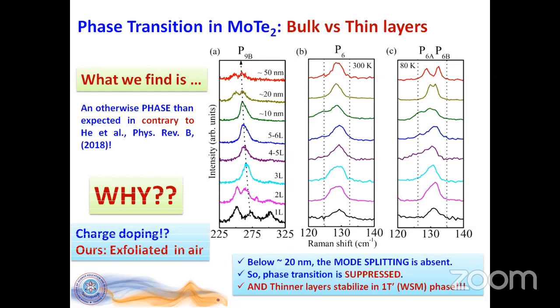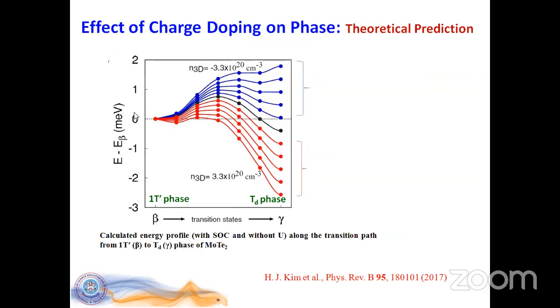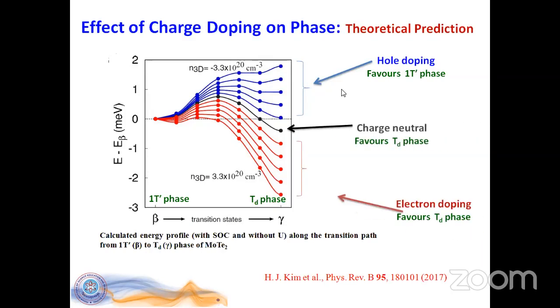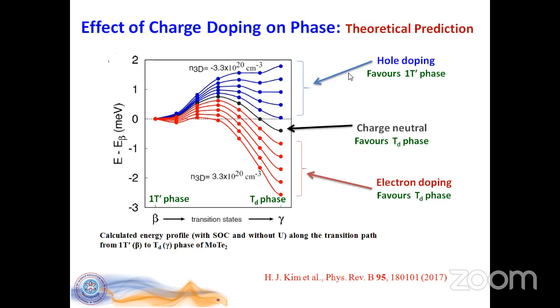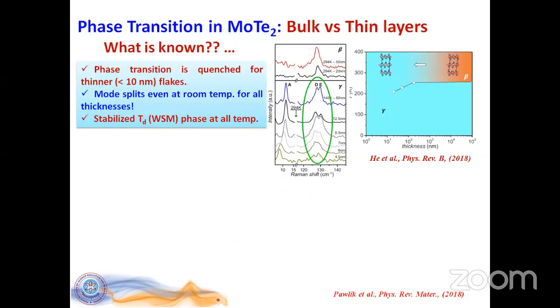Now, the question is, why is it so? Is it due to charge doping? Just to give you the information, our exfoliation was in air, and now let's see what some other people also predicted theoretically. So here is an interesting prediction, that if there is a charge doping, let's say electron to hole, in the hole doped system, it will be the 1T prime phase, which is the high temperature phase, that will be favored. On the other hand, when it goes to neutral or let's say electron doped system, it is the low temperature phase which will be favored. So that basically gives us some ideas about what could be happening.